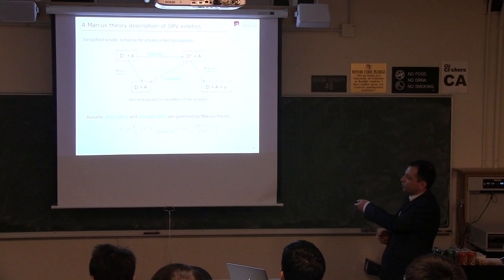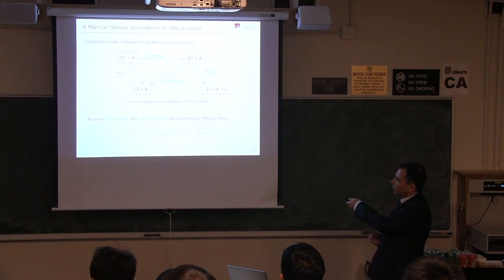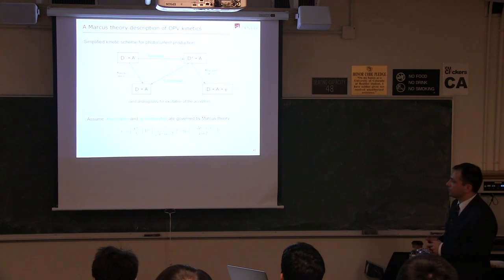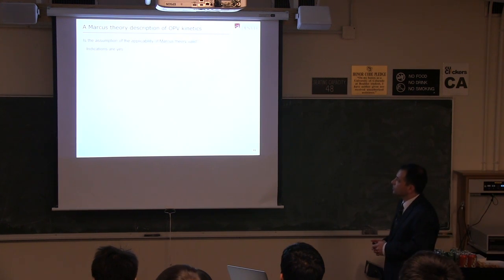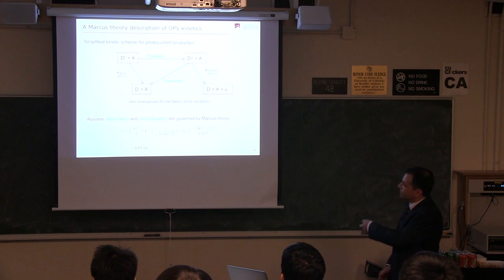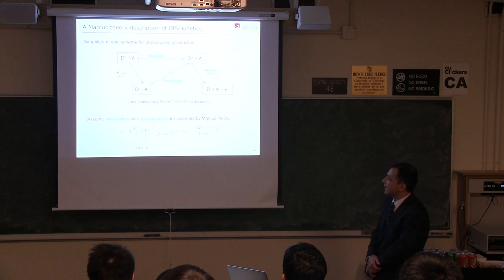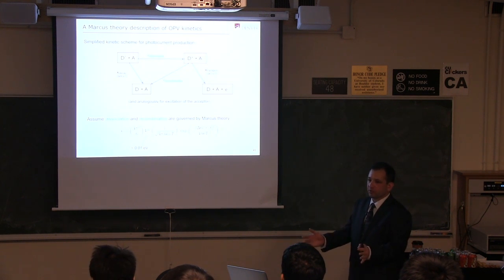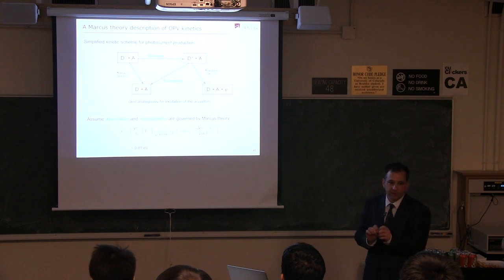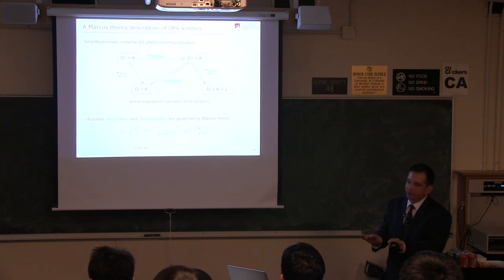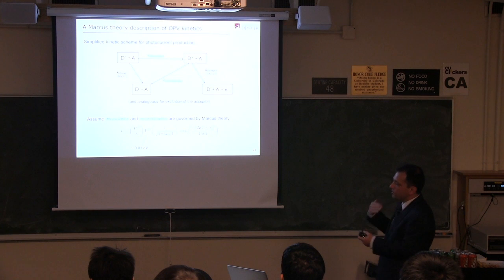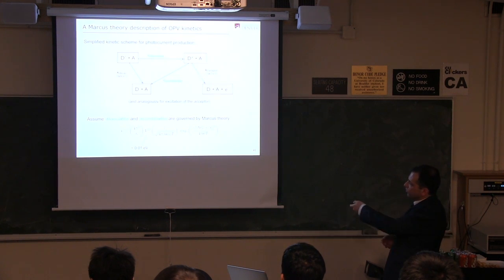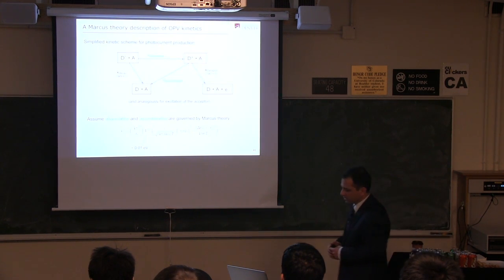So this looks like a parabola. You've got delta G plus this quantity lambda, and this is squared, so you've got a parabolic function. I wanted to point out something: lambda is very important. This is the reorganization energy of the system. So what is that? If you take a neutral molecule and put a charge into it, all of the bond lengths will change just a little bit, and there will be an energetic shift in the molecule. That is the reorganization energy upon the electron transfer event. So that is a critical component here, and I'm going to talk about that in a second.